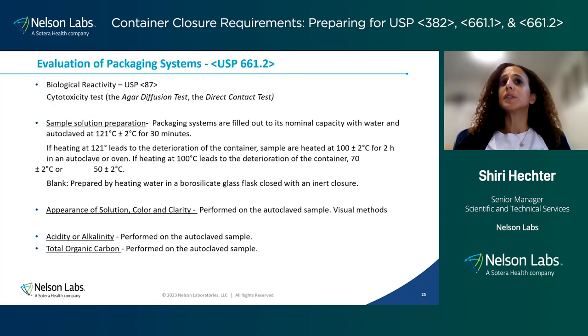661.2 details, like Logan said, the packaging system as a whole, not just the material of construction. And the first test that is detailed there is the cytotoxicity test, or the biological reactivity based on USP 87, and is really to measure whether there are any significant biologically harmful extractables in the packaging material. In 661.2, the sample solution for the remaining tests is prepared by autoclaving the actual packaging systems. The actual packaging system, the vials, the syringes, or the IVs, are filled with water to their nominal capacity, and autoclaved at 121 degrees, usually for 30 minutes.